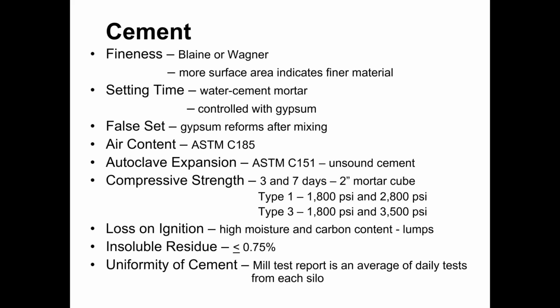What happens with unsound cement is that if the cement is used to make concrete while the cement is still hot from the manufacturing process, then it can over time lose durability. This unsound cement phenomenon was observed when cement plants had concrete block plants next door to them. That was very common in decades gone by, that the cement producer would also be a concrete producer. One of the items they would use their cement in would be concrete blocks, so they would have a block plant next door to the cement mill, and they would ship hot cement over to the block plant, which would then get used.